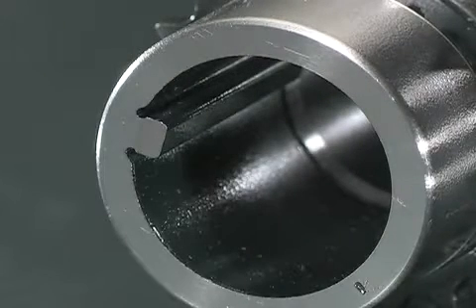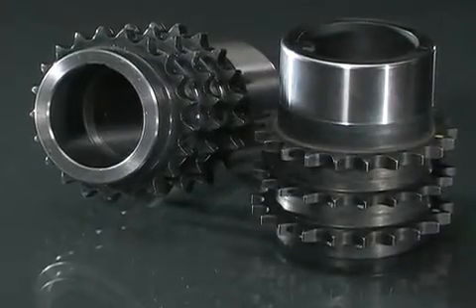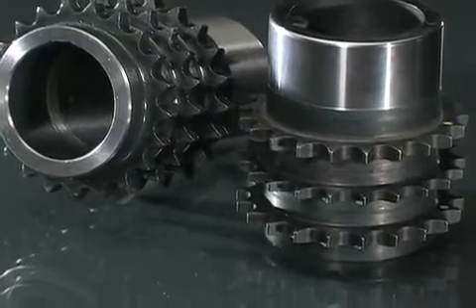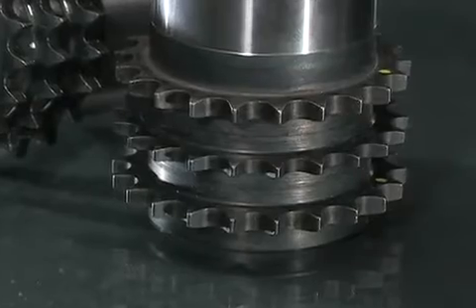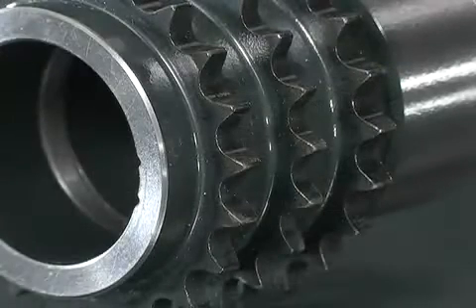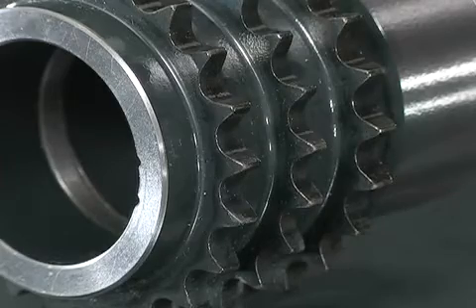It features an inner ring diameter that is pressed and machined after sintering to achieve high precision tolerances. Even with secondary operations, sizing, machining, induction hardening, steam treating, and final grinding on the lower hub, PM still provided significant cost savings for the customer.